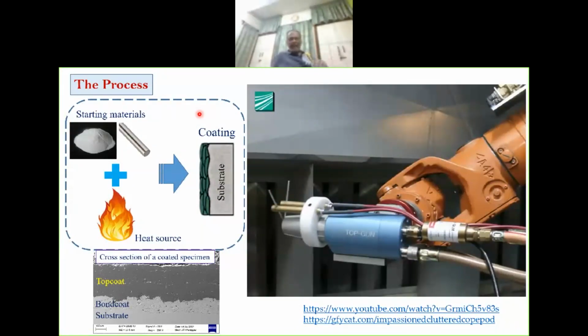Minimum thickness will be around 25 microns. How thick? We can go up to several millimeters. The industrial standard is something to the tune of 300 microns. Okay. Now, if you see a coating in a cross section, it will look like this.